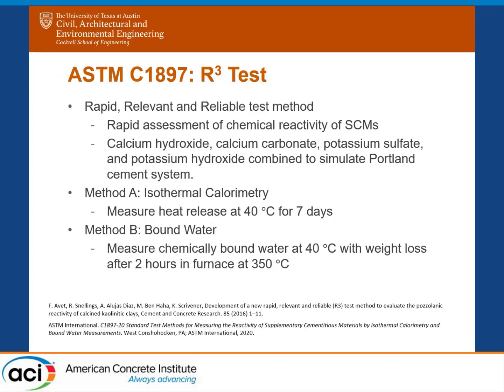So to test the chemical reactivity of these clays, the R3 test was used, which is the rapid, relevant, and reliable test method. So in this method, a Portland cement system is simulated using calcium hydroxide, calcium carbonate, and a potassium solution. There are two components. There's isothermal calorimetry, where the sample is cast and run for 7 days at 40 degrees C, and the heat release is measured. And then also a bound water component, where after those 7 days, the weight loss is measured in a furnace at 350 degrees C, and this is to measure the chemically bound water.